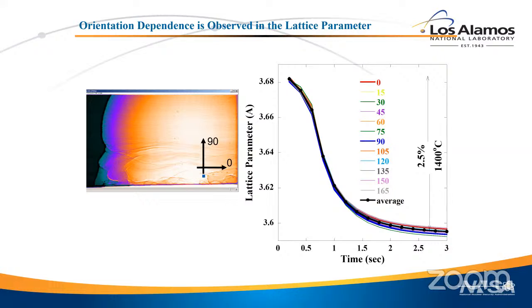That spread in lattice parameter as you get out to long time isn't random. That's not uncertainty. If you look at it at 0 degrees, the red is up high. At 90 degrees, it's low. So if this is the base plate, 90 degrees is normal to the base plate, 0 is parallel. What you're seeing there is the residual stress developing as it cools. As it cools, it tries to contract. In the plane of the base plate, it doesn't want to let it contract. It's constrained, so the lattice parameter is actually stretched. So at 0 degrees, the lattice parameter is bigger than the average. At 90 degrees, it's smaller, again, because of the Poisson strain effects. It's actually unconstrained in the vertical direction. So the average of that tells us the temperature. The spread of it and the nature of that spread tells us how the internal stress is developing as this liquid solidifies and cools.